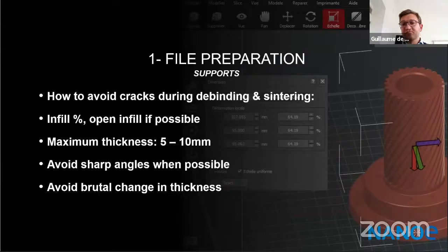Well, if we put an infill in the part, that means the part is not fully dense. Inside, we're going to put a gyroid or any kind of grid or whatever infill you want, but we will avoid having a fully dense part. If possible, we're going to try to make this infill accessible for the debinding. So if it can be open on one of the sides of the part, it's even better.